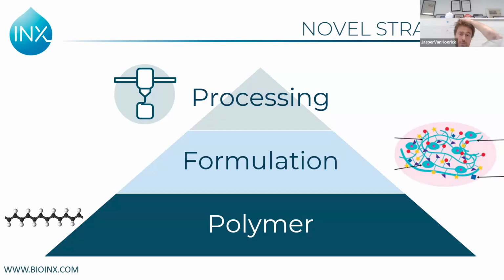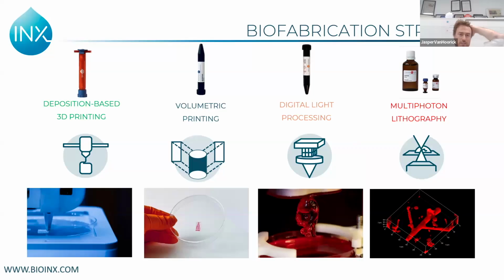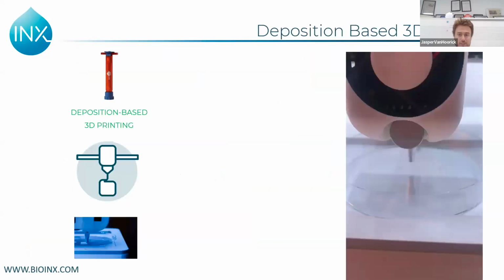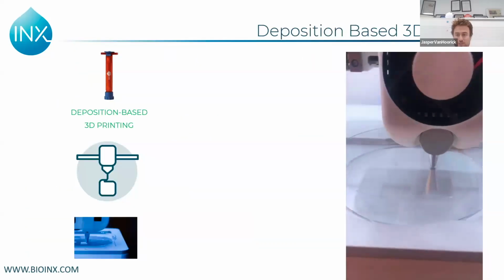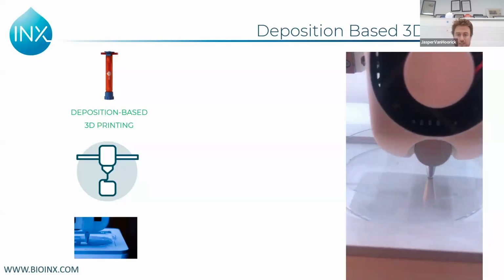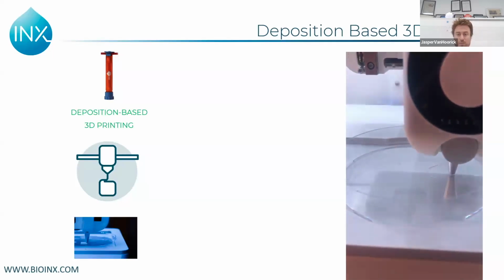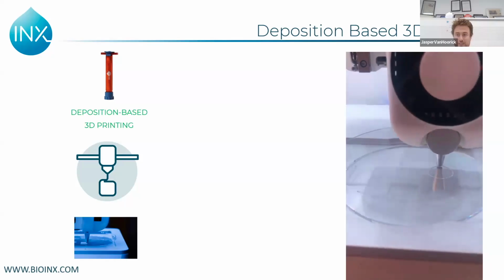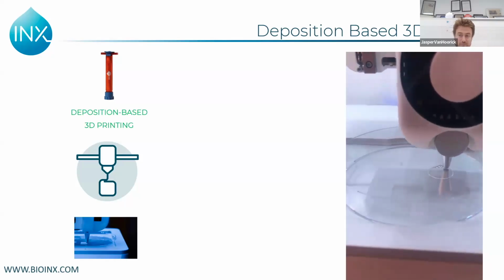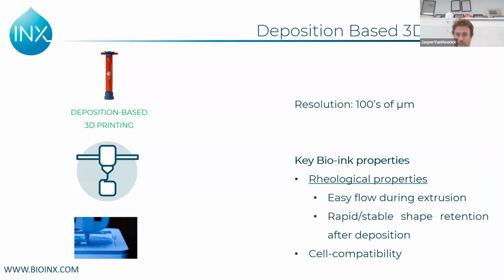So let's start with the most common one, which is extrusion-based bioprinting or deposition-based 3D printing. This is the one most similar to the commercially available 3D printers, and basically works by depositing your material in a layer by layer fashion, just on top of each other. So what do we have here? Resolution wise, it's the lowest resolution technology. It's hundreds of micrometers. Let's say in practice with hydrogels, 400 to 500 micrometers are about what you can get at. But to get there, your bio ink needs to have specific properties.